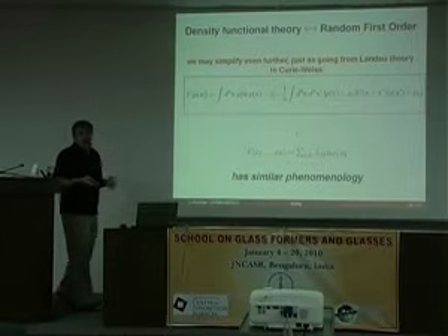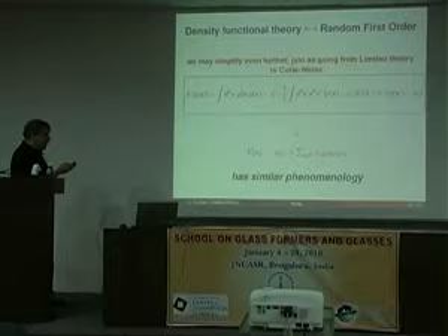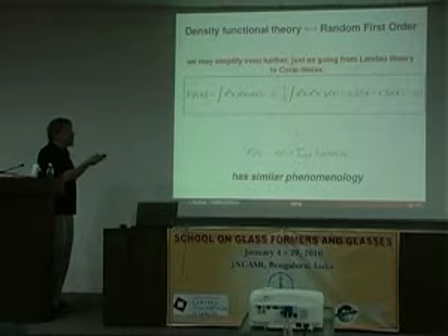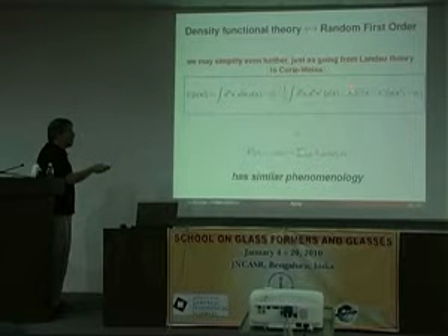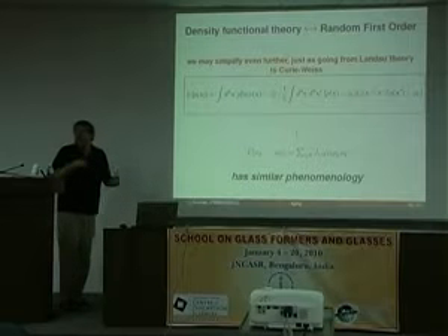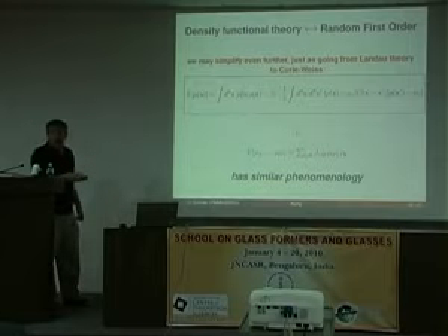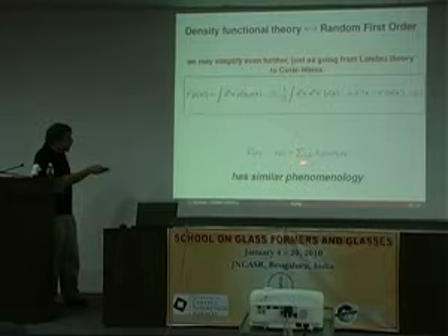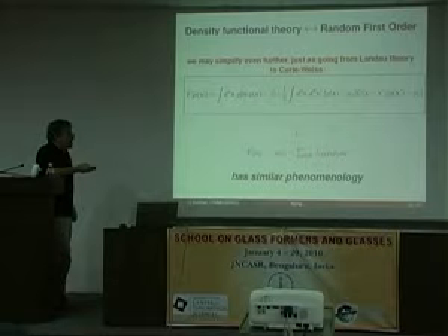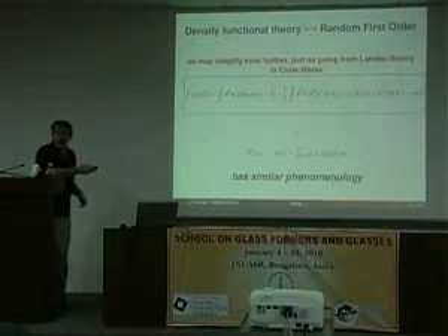The story is longer, and I'm going to go through it, but you've already seen it two or three times. The idea is that what Kirkpatrick, Thirumalai, and Wolynes realized is that you could model this, rather than having space and all the problem, with a discrete set of variables interacting through a random interaction, which is, for example, cubic, 3-spin. And this thing is a caricature of this. It is fully connected, so everybody interacts with everybody via a random interaction. So these are the models that are usually called random first order, but this is as well a random first order theory, provided this correlation is calculated self-consistently.